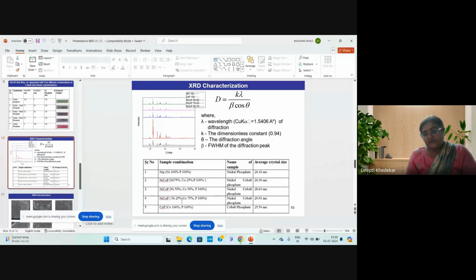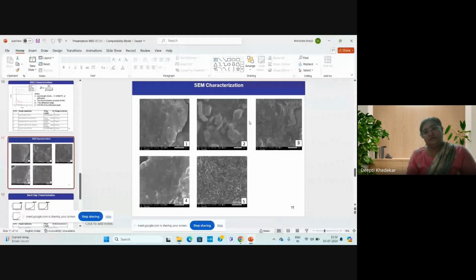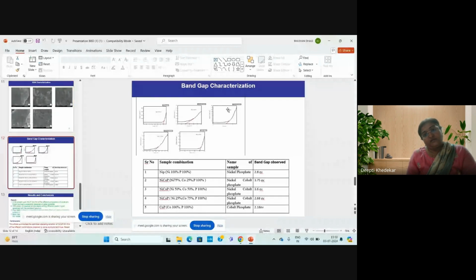Nickel 50% and cobalt 50%, we got 29.91 nanometer. And cobalt 100%, we got 25.54 nanometer crystal size. For all these prepared samples, we kept the concentration of phosphate constant. These are the SEM images for the 5 prepared samples. They show continuous, crack free and good films.